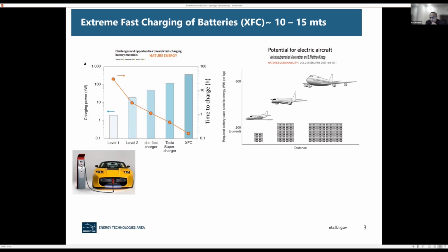When you decrease the charging time to 10 to 15 minutes, the power, if you look here, the time to charge dramatically decreases, let's say to 15 minutes, but the power is huge. It goes almost to the order of 300 to 400 kilowatts you need to pump into the battery pack. So there are going to be a lot of thermal challenges. You'll be generating a lot of heat as well while doing that.